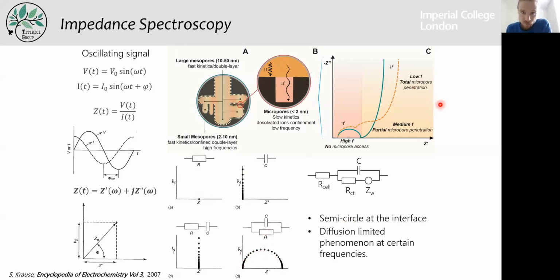So what we observe in most supercapacitors when you do impedance is basically a semicircle that corresponds to the interface. It depends which interface you're looking at. And then a vertical line that is not always exactly vertical, but that corresponds to the capacitive domain. And if you have a region in between the semicircle and the vertical line that is kind of a line, or that is not really a semicircle, then it probably means that you have a diffusion limitation in this range of frequencies, and that can tell you a lot about your pore structure. And this diffusion limitation is basically given by this Warburg component here on the electrical circuit.